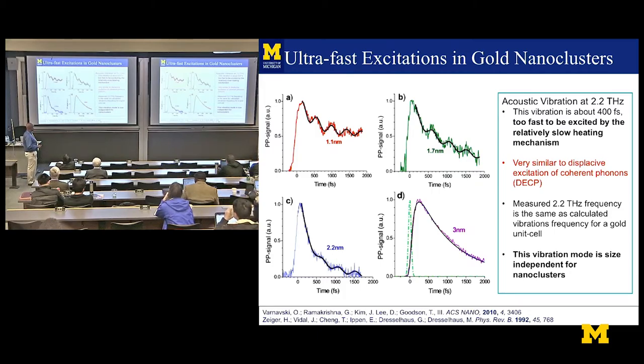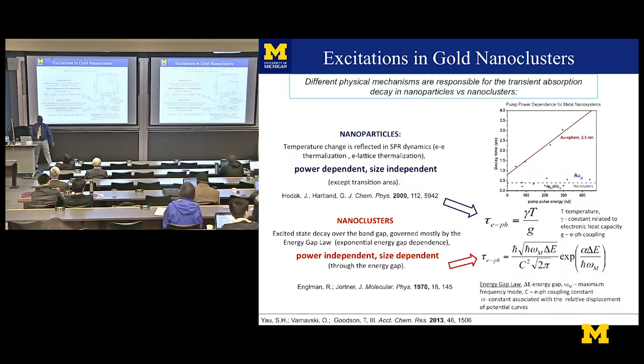What does that mean? It means if you measured the frequency and you calculated the vibration frequency of one gold, sulfur, gold unit cell, you can calculate that. The vibrational frequency mode seems to be about the same as the unit cell itself. It looks like a molecule of gold, sulfur, gold. Interesting. All right, and so it is not heating like you would expect in a big particle.